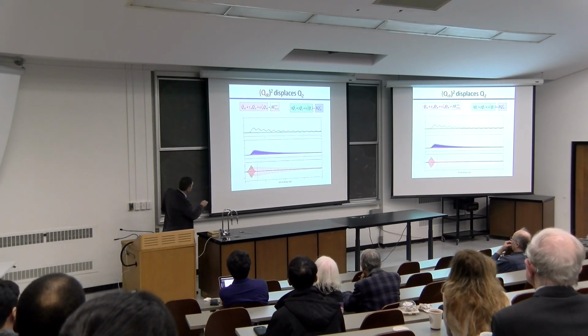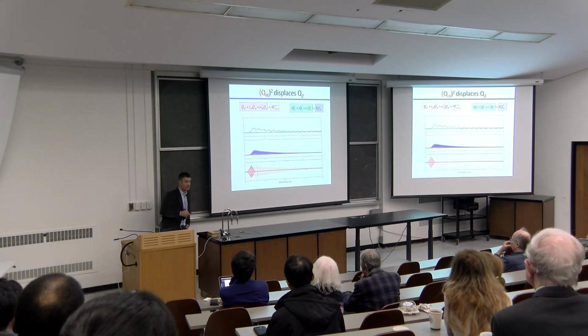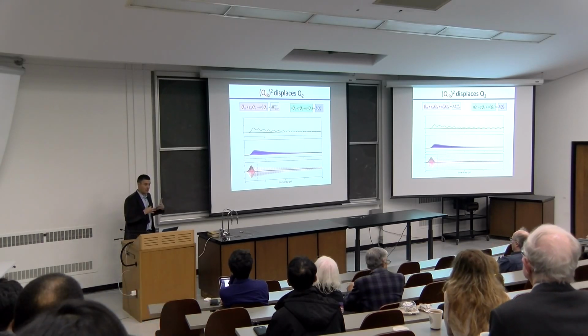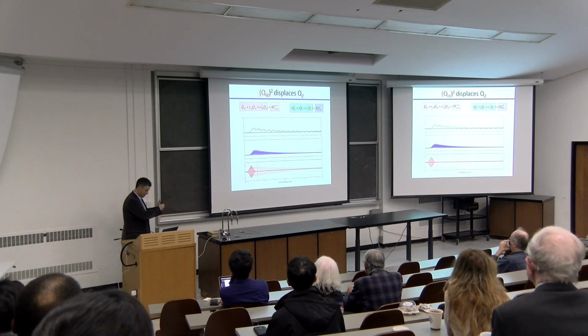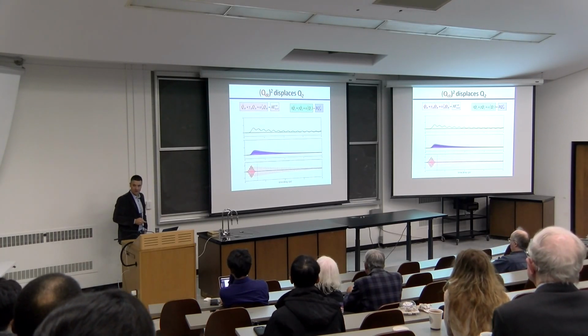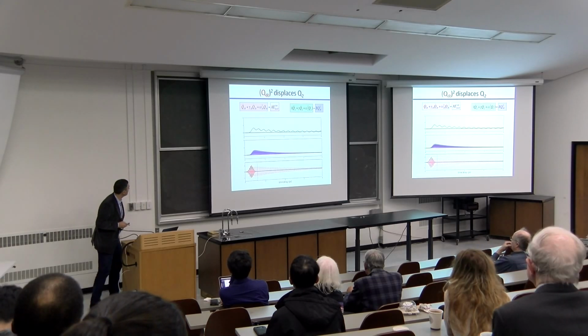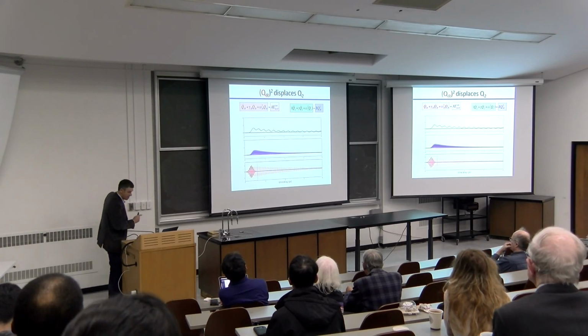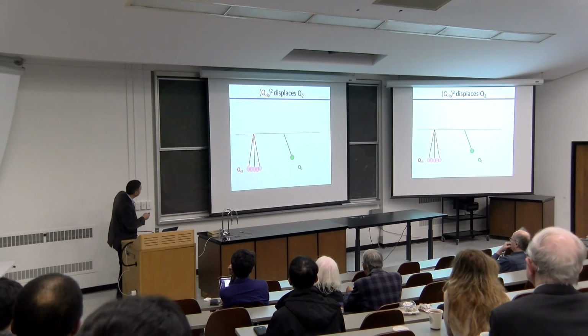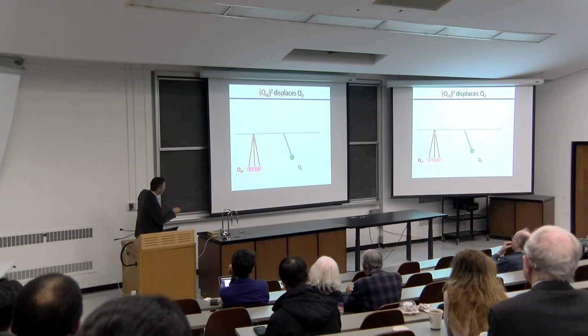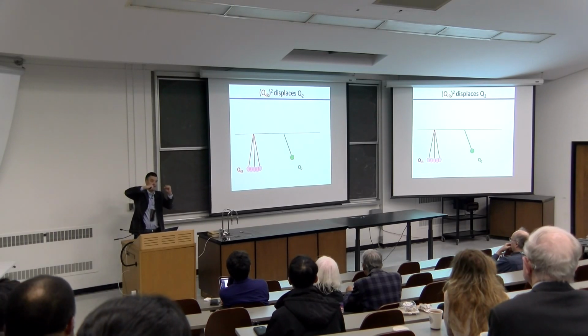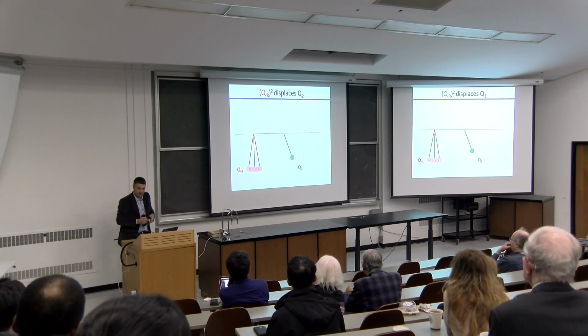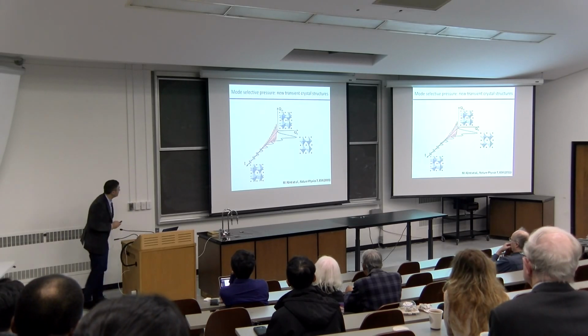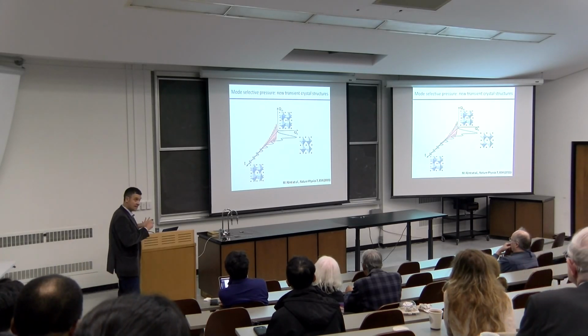And so the green mode can be pushed in one direction. This is the equivalent of optical rectification in nonlinear optics. For those of you that know a little bit about nonlinear optics, this is observed routinely. I can apply a sine wave to a quadratically, a second order nonlinear material and rectify the field. Okay? So this is equivalent also to saying that I have two pendula, one that I'm driving directly, and the second one which is coupled in that way, and as long as I'm shaking one, the other one stays tilted at a finite displacement.